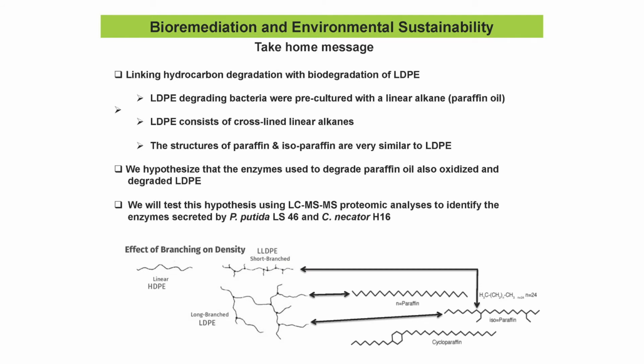And so the take-home message for this is that there's a link between hydrocarbon degradation and plastic degradation, because after all, plastics are hydrocarbons that are cross-linked, right? Polyethylene is basically linear alkanes that are cross-linked. So it makes sense that the enzymes that break down hydrocarbons can also attack the polyethylene. Although this is a hypothesis that's still yet to be proven, we need to do proteomics and understand which enzymes are being secreted when the bacteria is growing on hydrocarbon, and are they the same enzymes when it's been converted to grow on polyethylene.